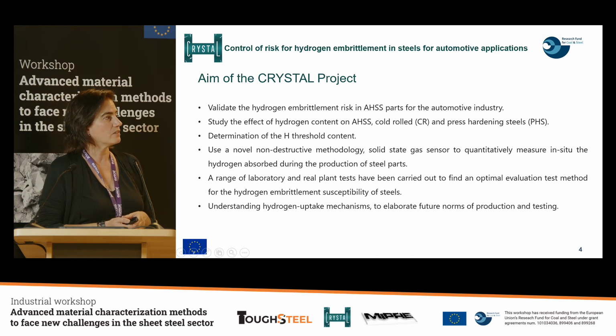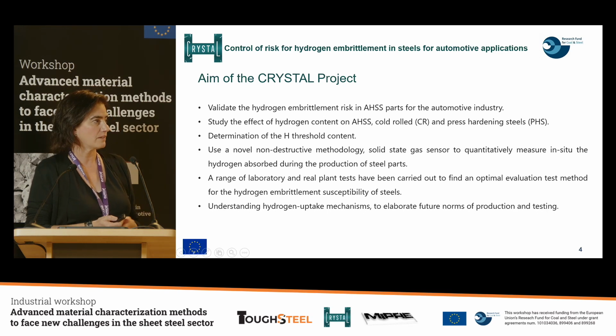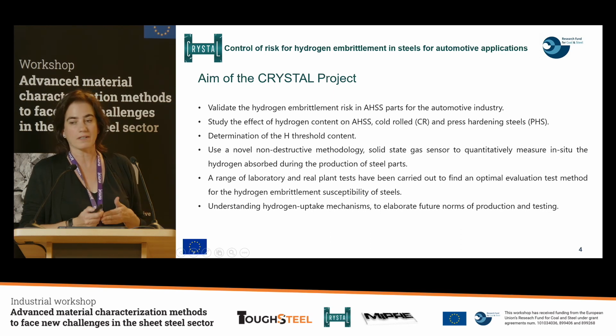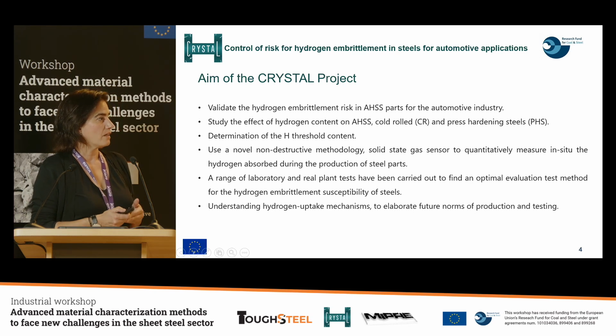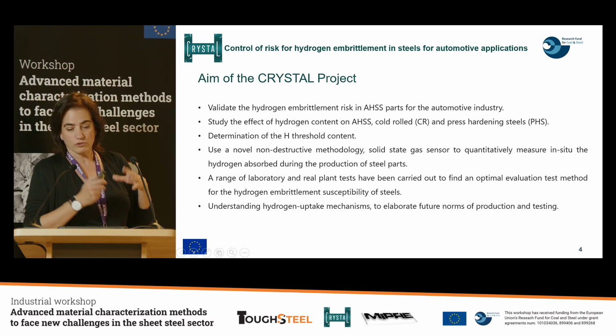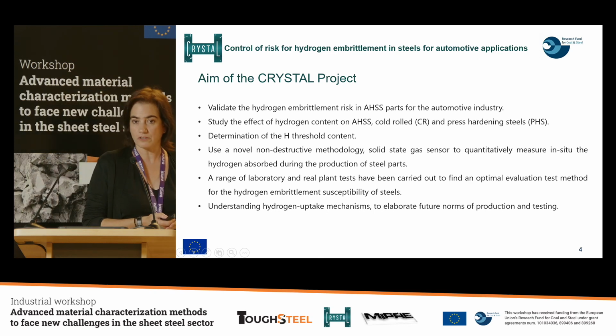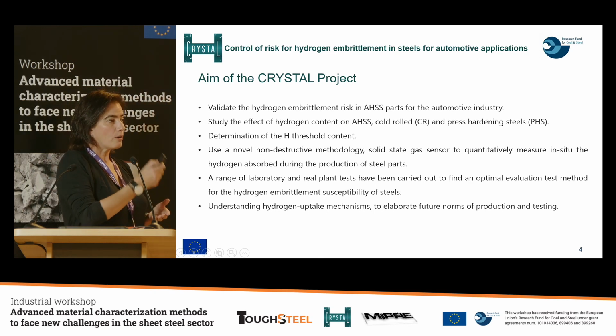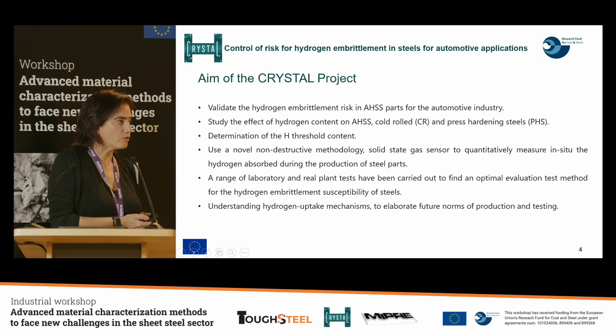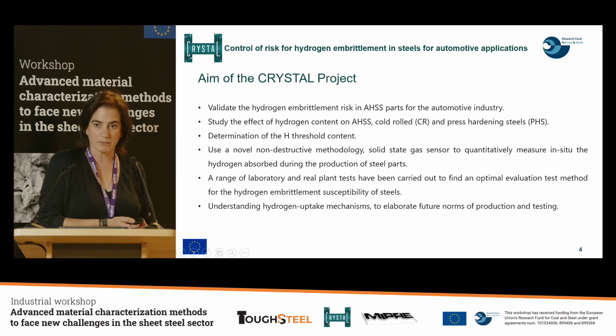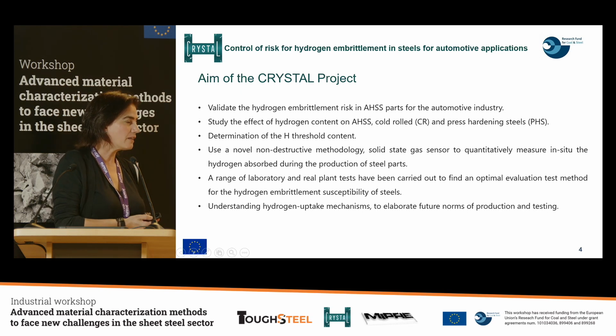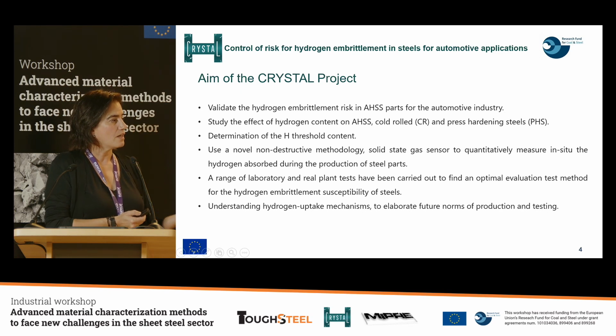Use a novel non-destructive methodology, in this case a solid-state gas sensor, to quantitatively measure in situ the hydrogen absorbed during real production steel parts. The 5th objective is to perform a range of laboratory tests and also real plant tests to find which is the best method to determine the hydrogen embrittlement susceptibility of this type of steels. And finally, the last objective is to increase the understanding of the hydrogen embrittlement uptake mechanisms to elaborate future norms in production and testing.